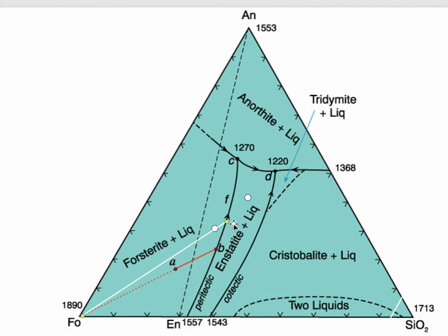So when it's solid, we don't really care about this forsterite plus liquid part. All we care about when it's solid is that dashed line and which side of the line it's on. And since it's on the quartz-rich side, or the silica-rich side, there will be no forsterite left. It will start out making forsterite, but it won't have any forsterite left when it's done.